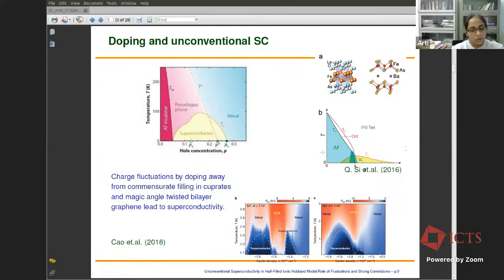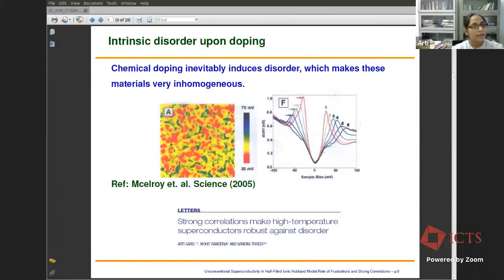Now, there is a very important issue about this doping away from the commensurate filling, and that is that the chemical doping away from the commensurate point actually induces some kind of disorder into the system and makes these materials really inhomogeneous. And why is it so? Because we are starting from a parent compound which is a Mott insulator. So any kind of chemical doping will produce a potential which will not get screened easily, and the system feels a large inhomogeneous chemical potential.